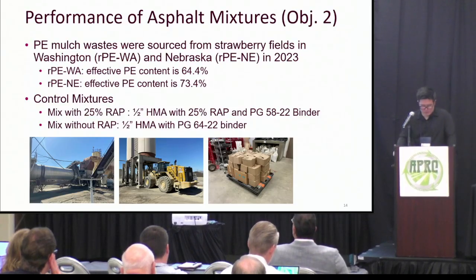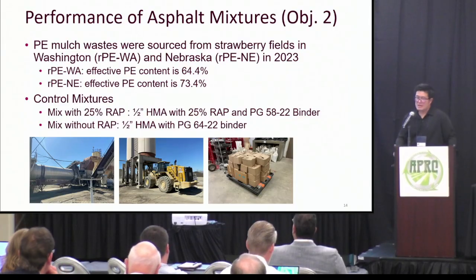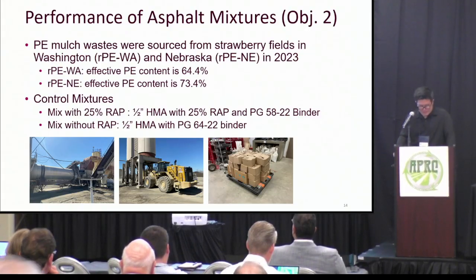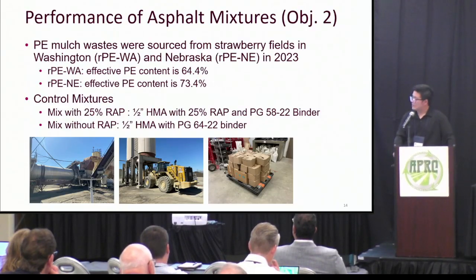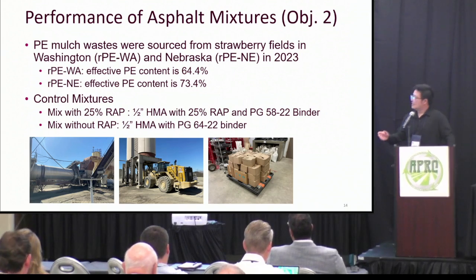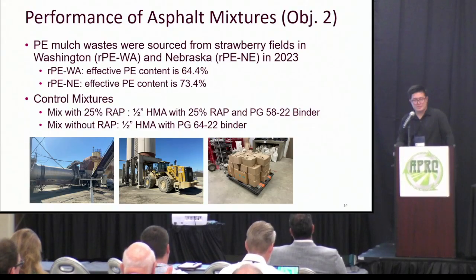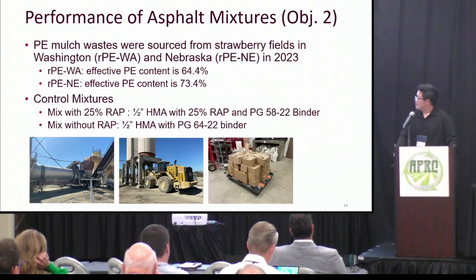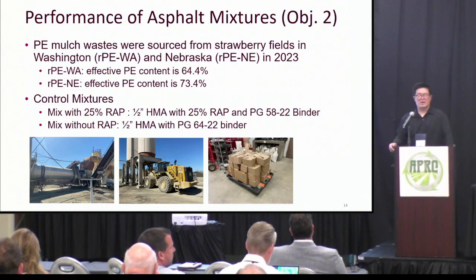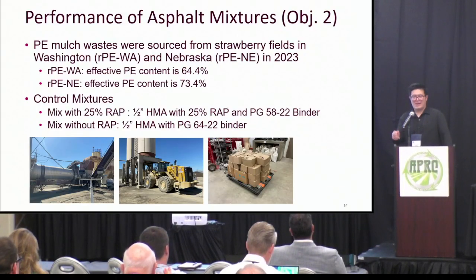So now moving to the performance evaluation of asphalt mixture, which corresponds to objective 2. We conducted a series of experiments using PE mulch waste collected from strawberry fields in Washington and Nebraska. And we compared the PE mulch modified asphalts with two control mixtures. One control mix has 25% RAP, where RAP is recycled asphalt pavement. And the other control mix is without any RAP and without any plastic.